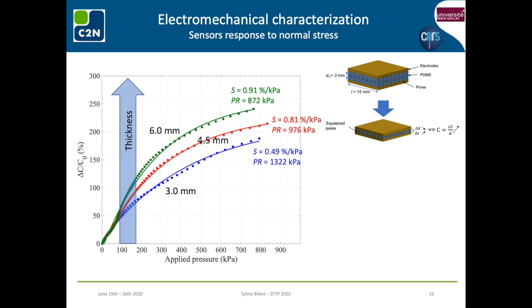Here, we compare the sensor response curves obtained under increasing loads for sensors made with the same scaffold geometry, providing 50% porosity, but with thicknesses of 3 mm represented by the blue curve, 4.5 mm represented by the red curve, and 6 mm represented by the green curve. We can clearly see that the thickness of the scaffold PDMS layers modifies the sensor performance. The sensitivity increases with the thickness and the pressure range decreases with the thickness.